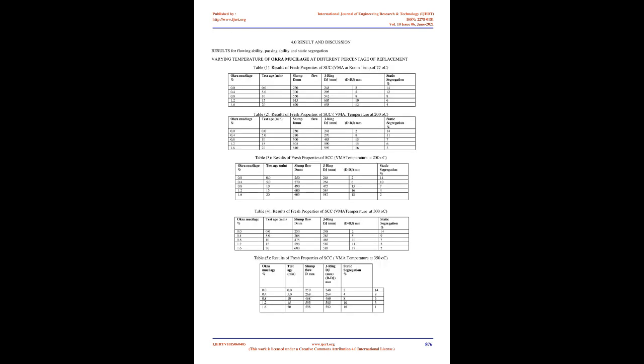Viscosity modifying agent, Okra Mucilage, a viscosity modified admixture. Okra Mucilage admixture was used to develop concrete with enhanced viscosity and controlled rheological properties. 3.2 Experimental method. A cement content of 356 kg/m³ was used for the self-compacting concrete. Water was adjusted to yield a slump of approximately 75 mm at 27 degrees Celsius. This resulted in a water-to-cement ratio of 0.45. These mix designs were held constant throughout the program.